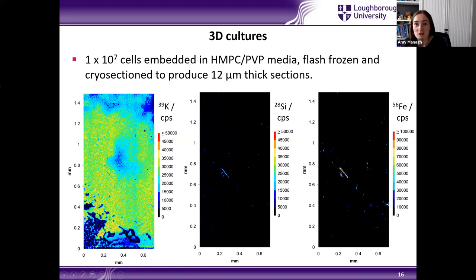When you see the tissue section under the microscope, you can't actually see whether there's any fibres present because those fibres are well embedded within the tissue. I provided this sample to my PhD student as a blind sample, so I didn't tell him what type of fibres were present. When he did the analysis, he saw a range of fibres within the tissue. Most noticeable, this long one here, which is about 120 microns in length, and also some smaller fibres as well. From the elemental composition, he compared that to the previous data and was able to correctly identify that these fibres were amosite fibres in the blind sample.